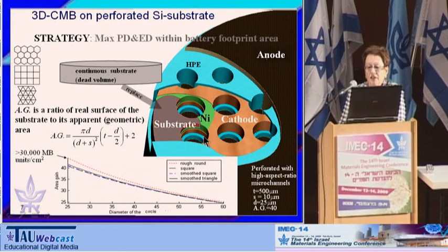In the case that the diameter of the microchannel is 25 micron, the interhole spacing is something about 10 micron, and the thickness of the substrate is 0.5 millimeter, the geometrical area gain is 23. By this is meant that we have more than 30,000 microbattery units per 1 square centimeter footprint of the battery.